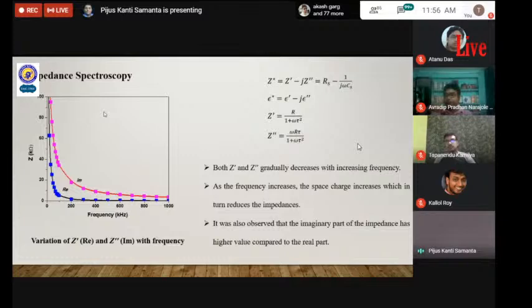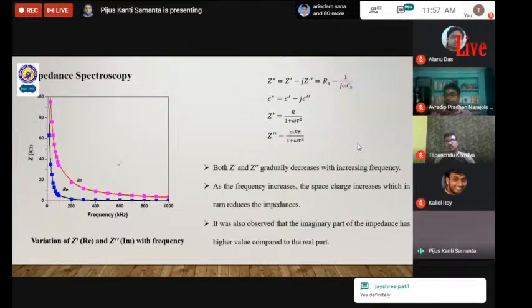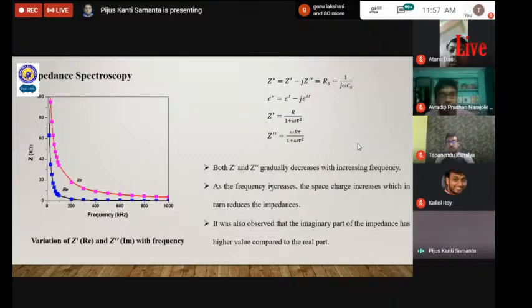We also studied the impedance spectroscopy to study the different contribution of grains, grain boundaries, and electrode-electrolyte interface effects on the impedance of the material. So this graph shows the frequency dependence of both the real and imaginary part of the impedance. And these formulas are well established, so I am not going into details. And this figure shows that both this real and imaginary impedance gradually decreases with increasing frequency. So as we know, as we increase the frequency, obviously the space charge increases, which in turn reduces these impedances. It is also observed that the imaginary part of the impedance has a higher value compared to this real part.